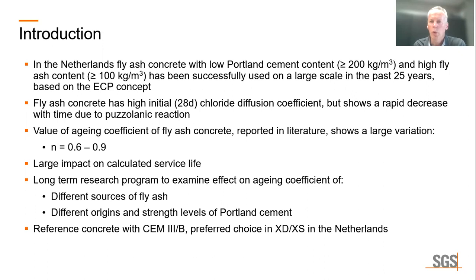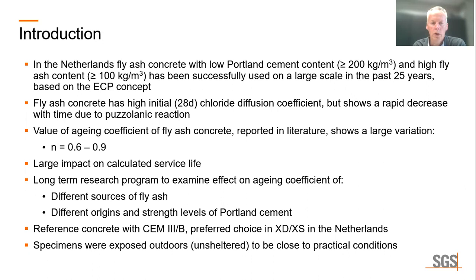In this program, we have used a reference concrete with blast furnace slag cement, which is the preferred choice in chloride-loaded environments in the Netherlands due to its high resistance to chloride penetration. All specimens were exposed outdoors, unsheltered, to stay close to practical conditions.